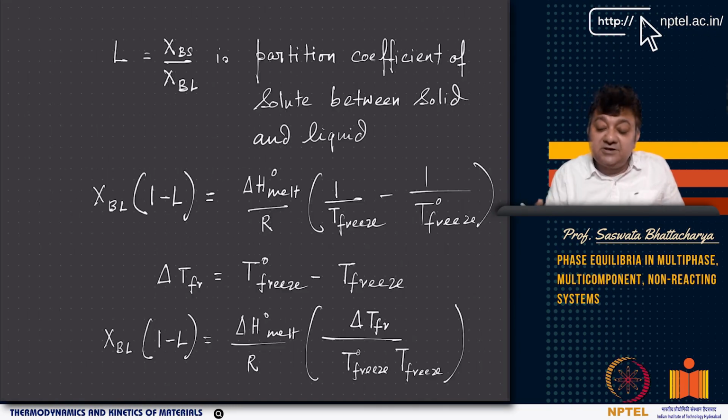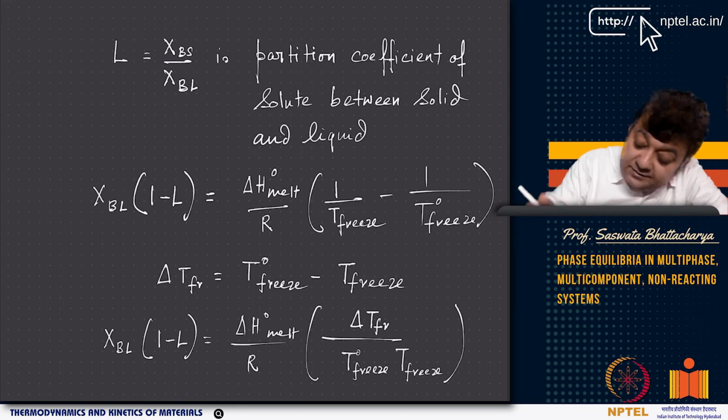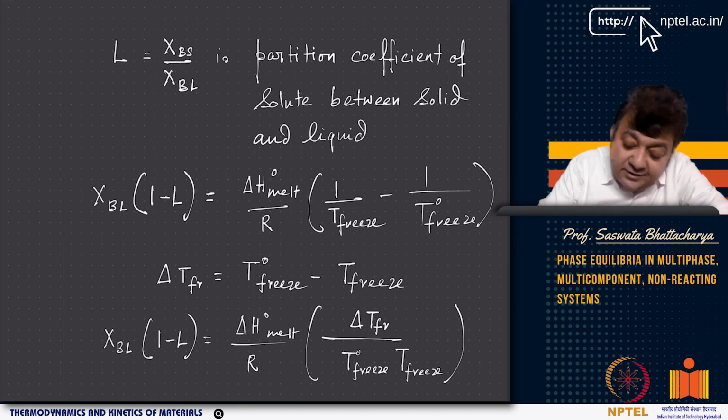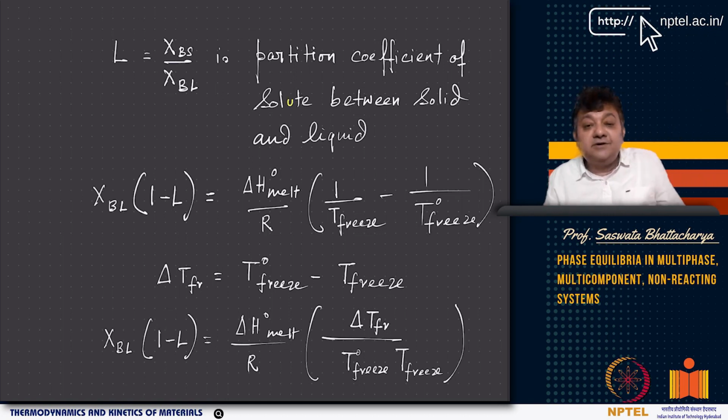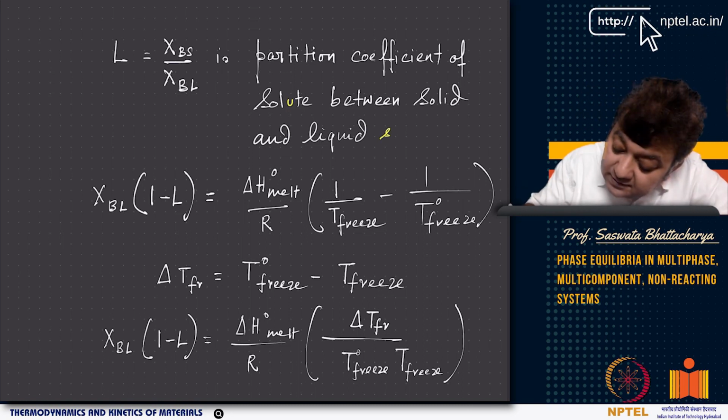Now XBS by XBL, we can call L, or you can call it P also, but here I have called it L. It is the partition coefficient, XBS by XBL, between solid and liquid solutions.